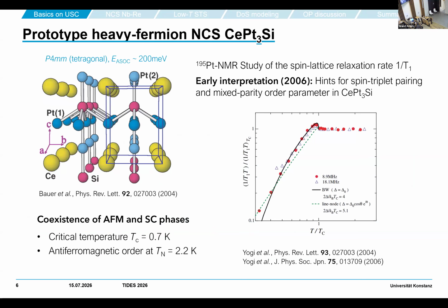We are not the only ones, or the first ones, investigating this. In fact, in the heavy fermion community this has been investigated already more than 20 years ago, and the prototype system where this was shown first is cerium platinum 3 silicon, where the first evidence came from NMR studies, specifically the longitudinal relaxation time study, where it was found that there is a coexistence of an antiferromagnetic and a superconducting phase, which could be described with triplet or p-wave components in the order parameter.